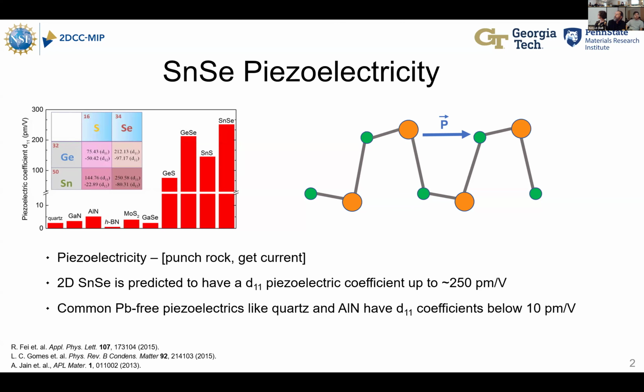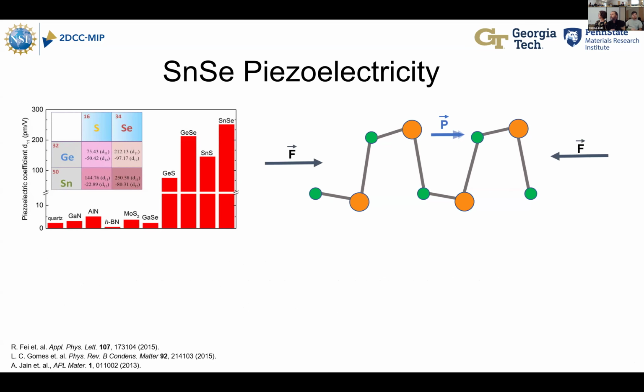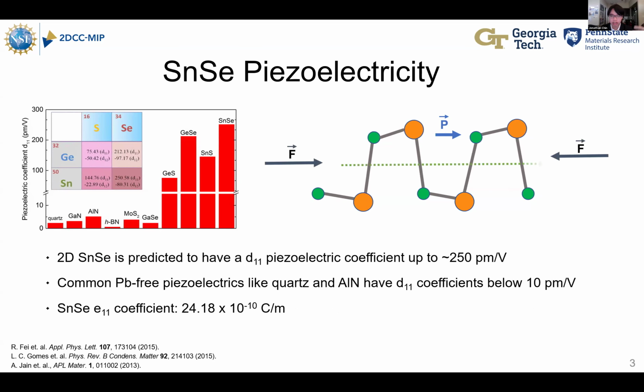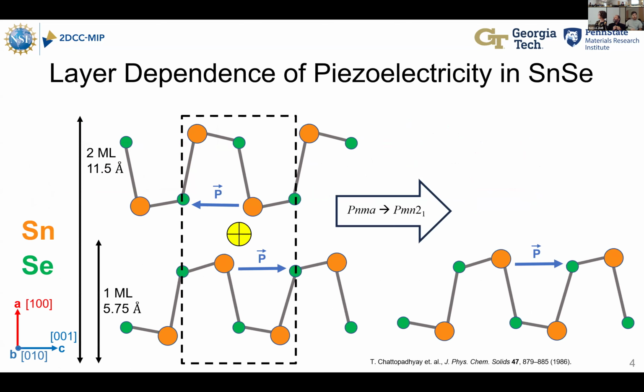Now, tin selenide is predicted to have a higher d11 piezoelectric coefficient than comparable lead-free piezoelectric materials like aluminum nitride or quartz. And it has a predominant polar direction along its 010 direction. So if you apply a force, you will get a strain in the material. This polarization will change, and that's how you can generate your current.